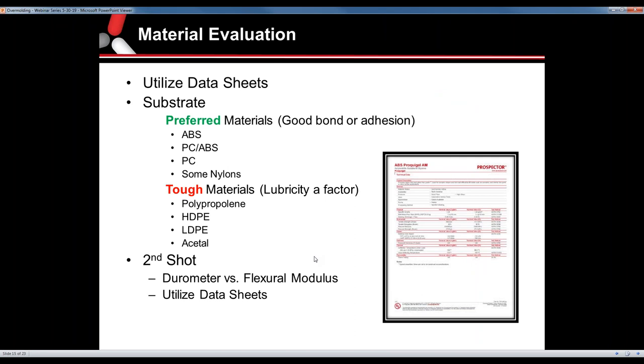On to materials: utilize data sheets. There's a lot of information on the web — a couple of good websites are Prospector and MatWeb. You can search materials and they should advise if they're good for overmolding and what materials they bond with. Typical materials for substrates are going to be ABS, PC-ABS, polycarbonates, and some nylons. Other materials that are going to be tough to overmold are polypros, HDPEs, LDPEs, and acetals — just due to the natural lubricity of those materials, getting another material to bond to them is going to be difficult.